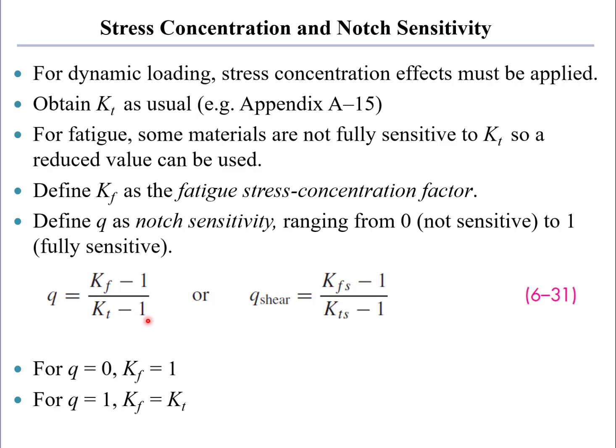stress concentration factor. If Q is 0, it means that the material is completely notch insensitive. So if it's notch insensitive, the fatigue stress concentration factor is just 1. If, however, Q is 1, then the material is fully notch sensitive, and the fatigue stress concentration factor is just equal to the elastic stress concentration factor. Values between 0 and 1 knock down the elastic stress concentration factor.